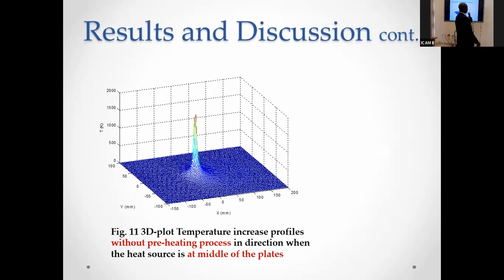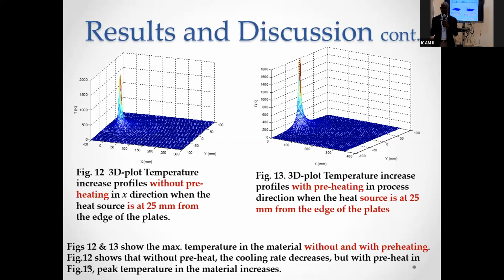Next slide. We also did a 3D plot for this, with preheat and without preheat. For without preheat, we put the temperature at the middle of the plate and we have this 3D profile. We've already done the 2D and we're also doing the 3D. Just look at the different points. This one is without preheat. We pick 25 millimeters from the edge of the plate and we pick the same way. This is the preheat. You see that the peak temperature is higher here than at this point.